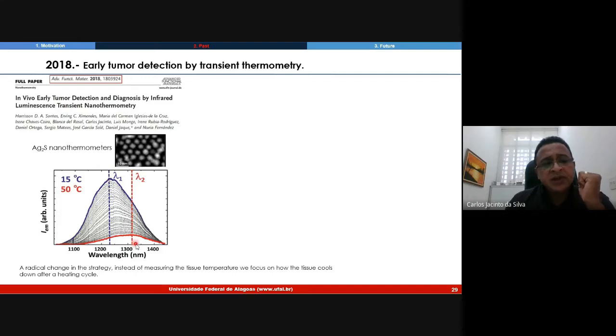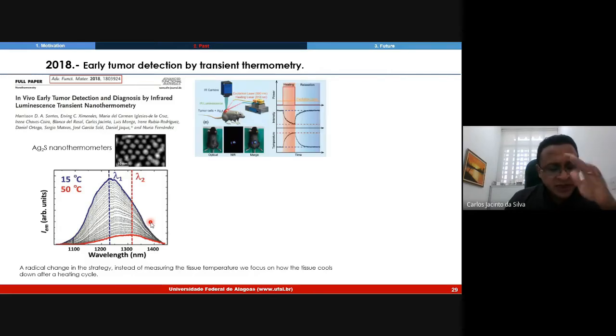For example, intensity, peak position, bandwidth. So it's a very interesting nanothermometer. But the idea is so simple. An excitation laser is used for tumor local heating, where the nanocrystals are located, and another laser is used to excite the nanocrystal. After heating, the heating pump is turned off, and the thermal relaxation is determined using the emission that is converted to temperature.